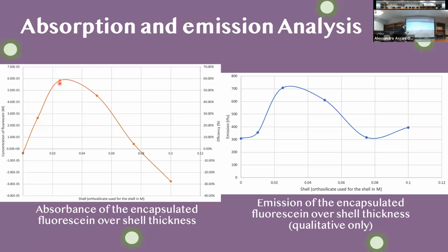Before that, the particles are still retaining some fluorophore, but the pore is still too big, and there is some leaching out from them. If we continue looking at the graph, what happens is that the pores start being filled up. There is too much silanol in the solution, and this essentially is occluding the pores, and it leads to a decrease in the absorbance, which then becomes essentially zero. And this is also confirmed by the emission analysis.